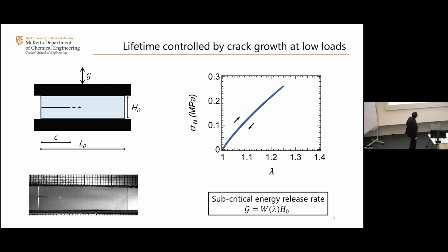Now, in reality, polymers and elastomers don't really go all the way to the fracture point during normal conditions. Most of the time, the system actually goes to very, very low deformation for an infinite number of cycles. By infinite, I mean something very, very large. So instead of taking the material all the way to the fracture point, you go through many stress-strain curves, or many cycles of loading and unloading.